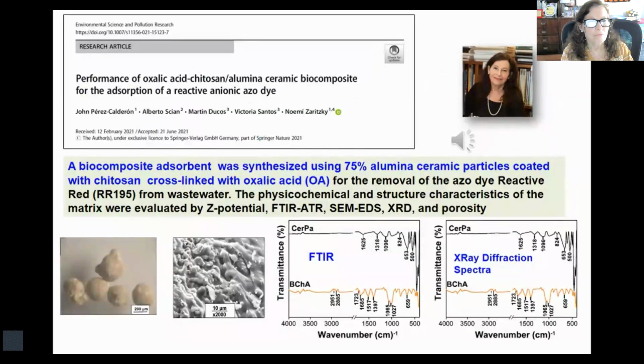In this work, a biocomposite adsorbent was synthesized using 75% alumina ceramic particles coated with chitosan cross-linked with oxalic acid. They were used for the removal of the azo dye from wastewater. The physicochemical and structural characteristics of the matrix were evaluated by Z potential, FTIR, scanning electron microscopy, X-ray diffraction, and porosity.